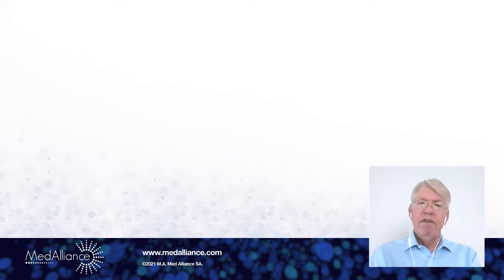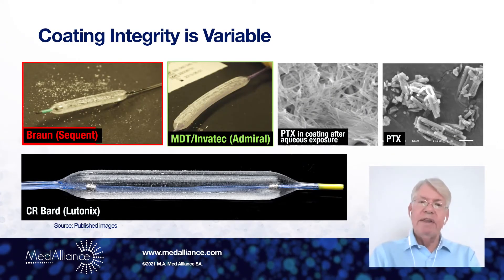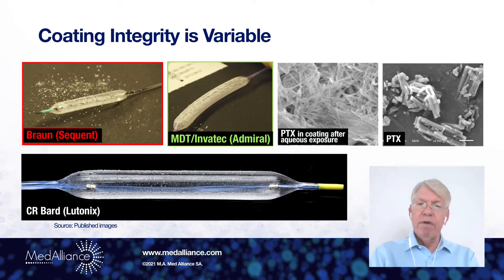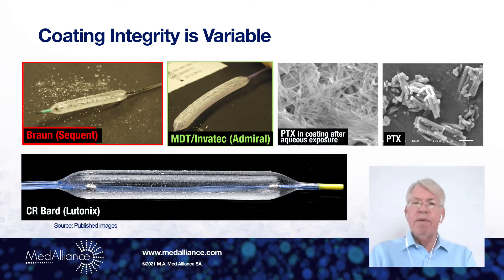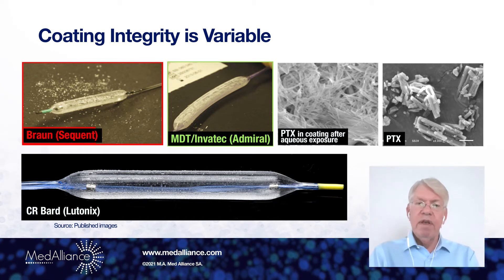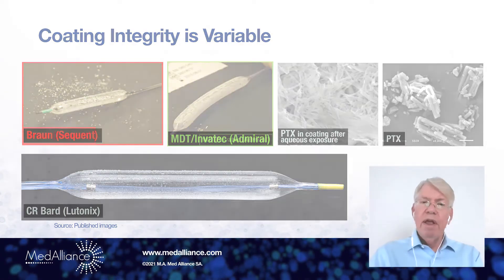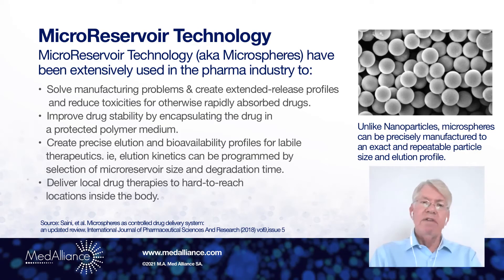This is just some pictures of some of the drug-coated balloons using paclitaxel, which use semi-crystalline or very crystalline coatings. You can see a lot of the drug and coating is actually released as particles, which then float downstream to non-target organs. So we tried to solve this problem by coming up with a new approach.